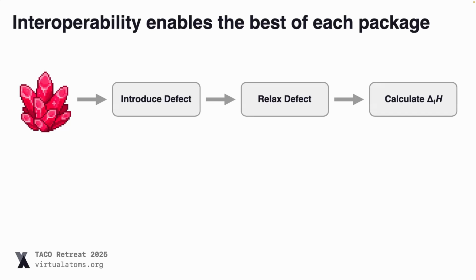Okay. The other thing which I think having these interoperable workflows enables is specifically when some DFT packages, for example, might do better in some cases than others. So the example that I want to give is in defect workflows. So the typical thing we would do in a defect workflow is we would take a crystal structure, we would introduce a defect, we would do a relaxation, and then calculate the defect formation energy. And typically we're using hybrid density functional theory for defects in order to get the correct localization of the wave functions. And this is very expensive in DFT. We're doing large supercells at hybrid level of theory.